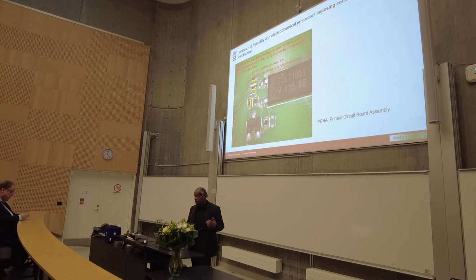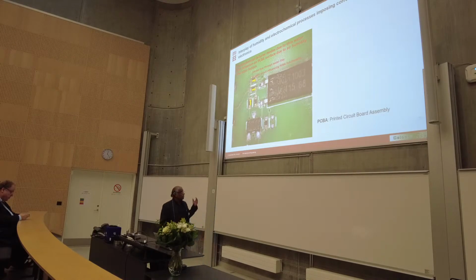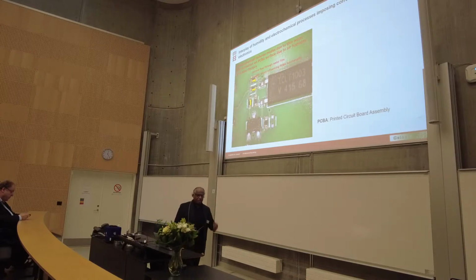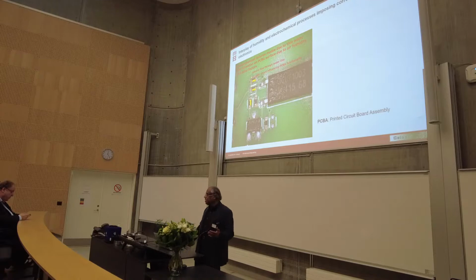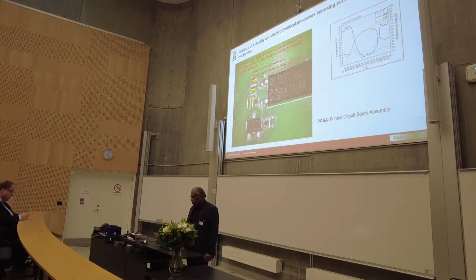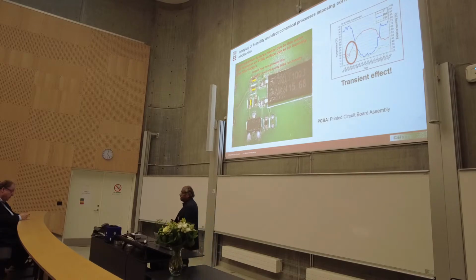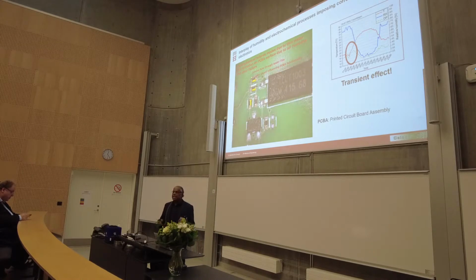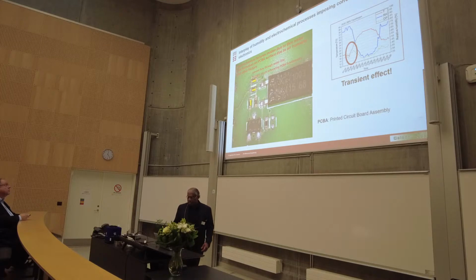One part of what we look at is humidity forming a condensed water layer on the board, and this condensed water layer acts as a parasitic current conduction medium. This happens because of the corrosion and electrochemical processes on the board, and that leads to different failures. Most of these failures are transient effects, which means that when that kind of condition exists from the environment inside the device, you get a sudden failure. It's not an aging failure, you get a sudden failure because of this effect.